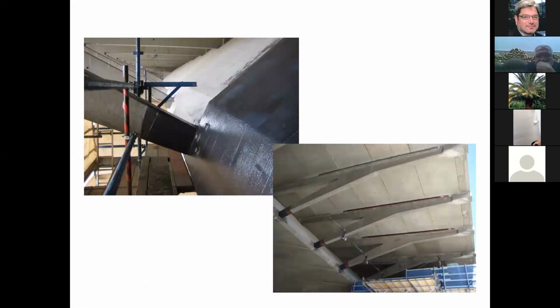This is where the web of the box girder meets the bottom flange. This is the bottom flange. Of course, the laminates cannot be bent because these are solid laminates. They stop here, and at the bottom here, they also stop. So what we do is we use splices. This splice here, we use carbon fiber sheets or carbon fiber fabric to ensure the continuity of force, continuity of stress transfer between the webs and the flanges. This shows you the lateral cantilever of the bridge, and this is the FRP strengthening system.